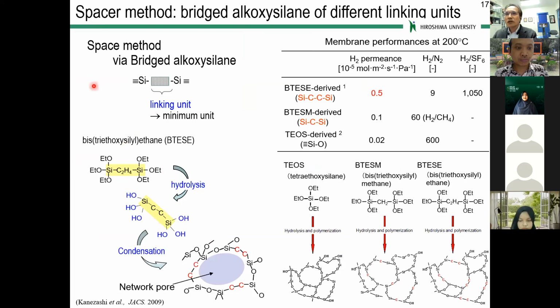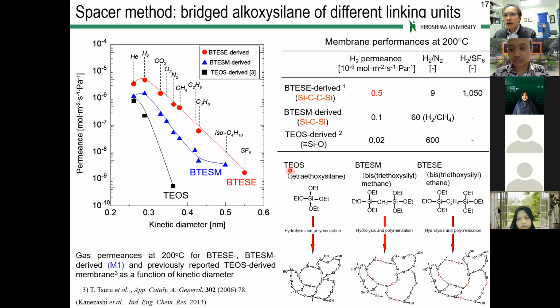Now, we proposed the spacer technique using bridged alkoxysilane in 2009, relatively recent. A typical bridged alkoxysilane is bis(triethoxysilyl)ethane. This precursor has 2 silicon atoms with ethane as the linking unit. This linking unit is stable in hydrolysis and condensation reactions, and stays in the network even after firing at 300 degrees C. So we expect the pore size can be tuned by this linking unit, just the minimum unit, like a Lego, right?